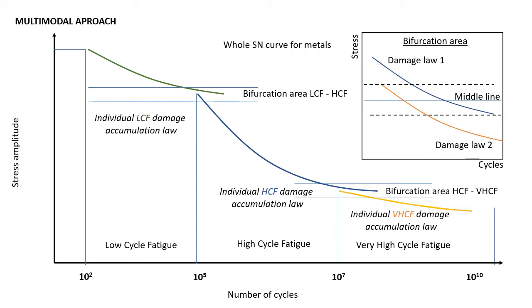Between the regimes can be introduced the bifurcation area where two different mechanisms are existing. A specific method of choosing the damage mode in such area should be established. In the present work, the uniform relation between stress and number of cycles, like a Basquin-type equation, was used for all three regimes, but the parameters of the curves were determined for each range, low cycle, high cycle, and very high cycle fatigue individually.